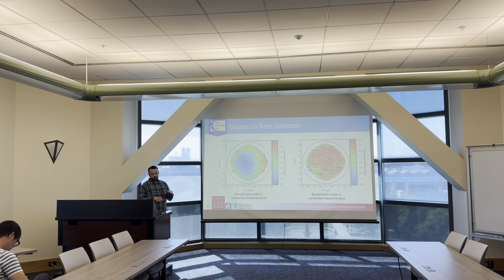Something else that needs to be considered when assessing the variation of device performance is the oxidation rate variation, and that's highly dependent on your method of oxidation. So on the left is the final oxidation extent variation for a 6-inch wafer that was oxidized in a conduction-based furnace. The temperature control relies on thermal contact with the heated chuck. So with 6-inch wafers that bow, you get a lower temperature in the center and higher temperature at the edge. That's why you have a longer oxidation extent at the edge, shorter in the center.